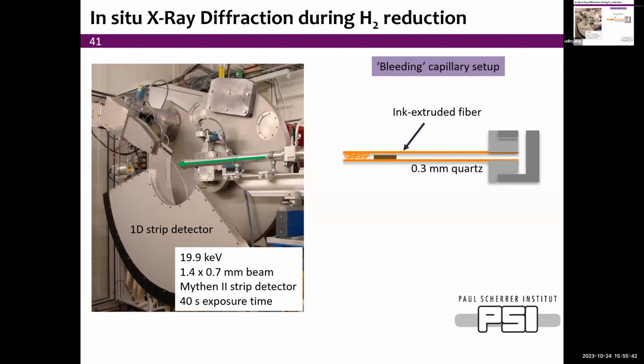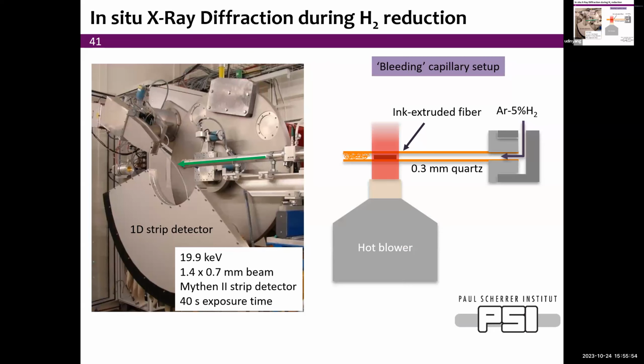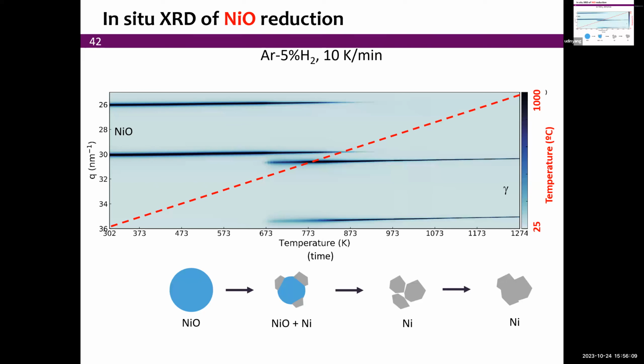And so the principle is relatively easy. You put your ink extruded fiber, so it has polymer and powders and oxide, and then you flush it with argon with 5% hydrogen. The hydrogen is sufficient to get you the reduction. You heat it with a hot blower to whatever temperature. You have, of course, a thermocouple, and then you have an X-ray beam that diffracts and will give us the identity of the phases as well as the volume fraction via the intensity of those diffraction peaks.